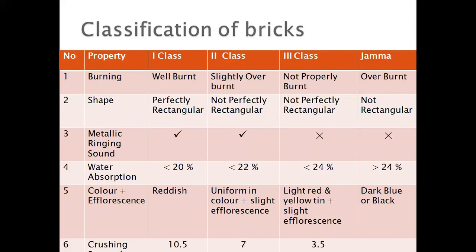For the water absorption test: weigh the brick, immerse it in cold water for 24 hours, then weigh it again. The increase in weight should not be greater than 20%, which classifies it as a first class brick. The color of the brick should be reddish. Efflorescence means gray or white patches on the bricks — in first class brick there will be no efflorescence. The crushing strength, tested in a CTM machine, should be 10.5 Newton per mm².